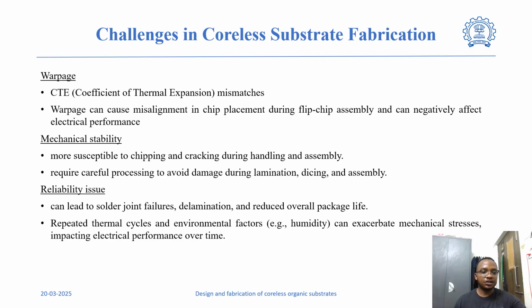There are also challenges like mechanical stability due to the absence of reinforcing core, which makes the substrate more flexible but also more prone to chipping and cracking during handling and assembly. There are also reliability issues due to long-term durability, and this is due to increased warpage and mechanical fragility that leads to solder joint failure, delamination, and reduced overall package life.